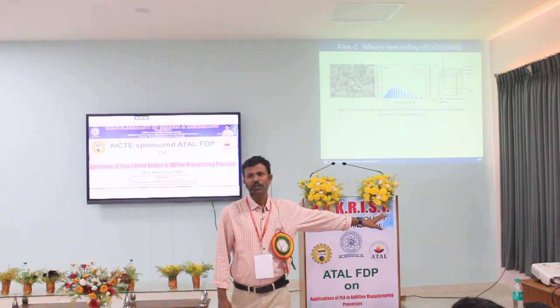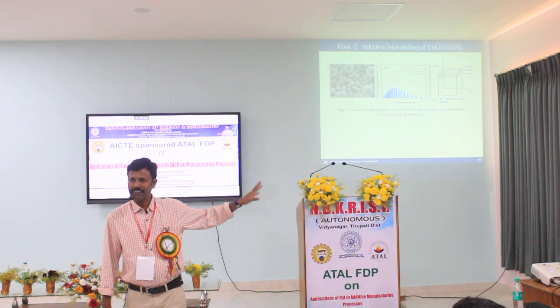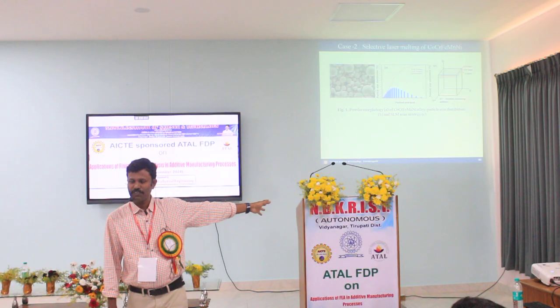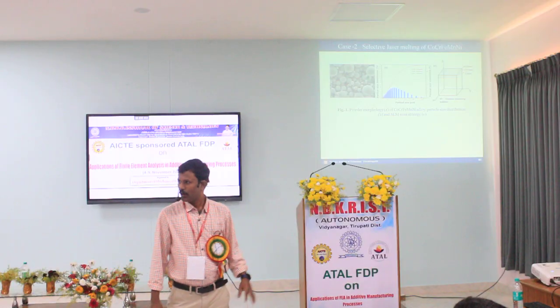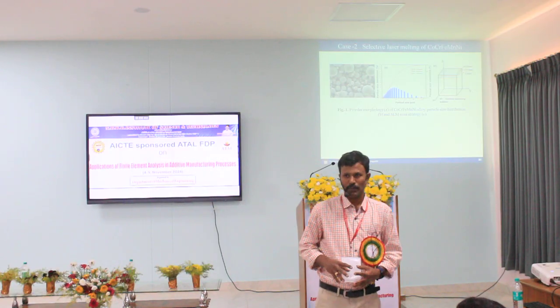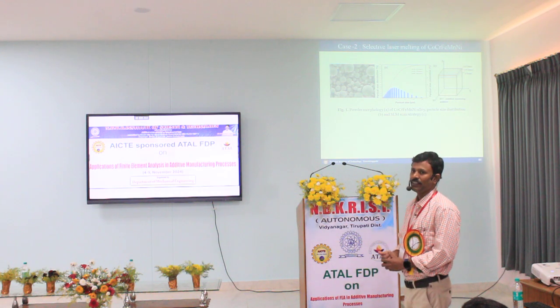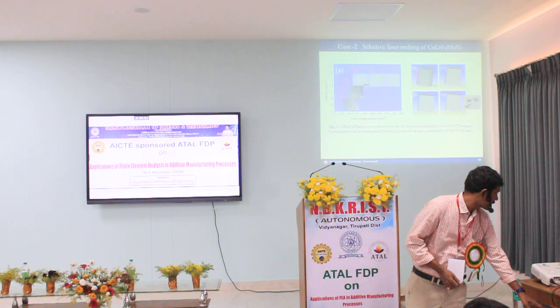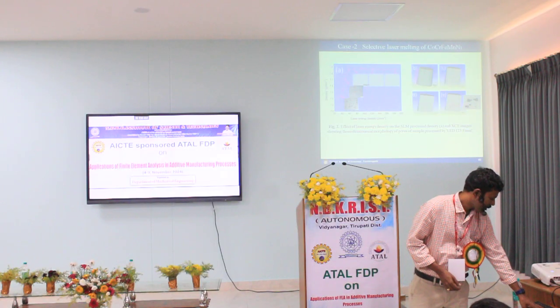Finally, we optimized it. We got 99.7% density. My first student in Estonia spent 1.5 years there to optimize this. Later he published 13-14 papers, but that is different. After optimizing, we found very fascinating and interesting results from this. So this is how the optimization was done.